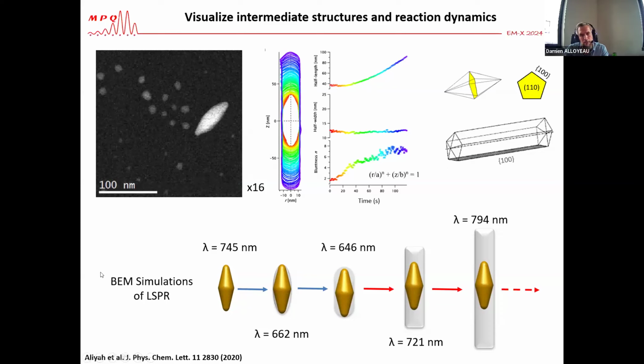And now if you run BEM simulation to simulate the absorption spectra of a given nano object, and you add this layer, transforming the bipyramidal seed into a nanorod with a pentagonal symmetry, you understand why you have this blue shift. And then once you have the nanorod shapes, you have the size increase of these nanorods, and the longer the nanorods, increasing the size of the nanorods induces the redshift. So you see that the possibility to visualize the intermediate structure and the reaction dynamics allows us to explain well what's going on at the bulk scale and in the beaker of our colleagues.